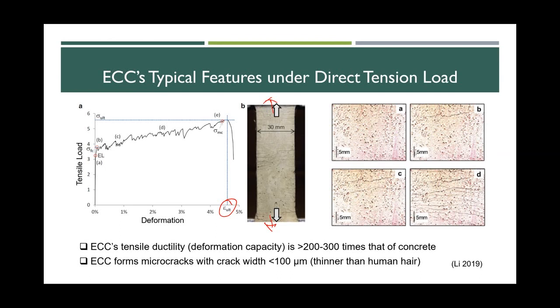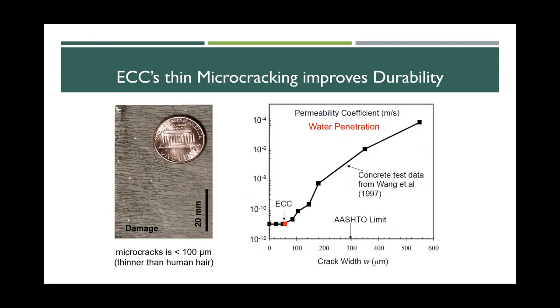To give a sense of what 100 microns actually means, the thickness of your hair is 100 microns. So you see the cracks in this picture, the thickness of each crack is actually thinner than a human hair. With such thin cracks, or very well controlled cracks, you can improve the durability of the bendable concrete. Again, you see compared with the penny, the microcracks are very, very fine. And we did a water penetration test because water is one of the causing factors to mess up the concrete, the reinforced concrete.